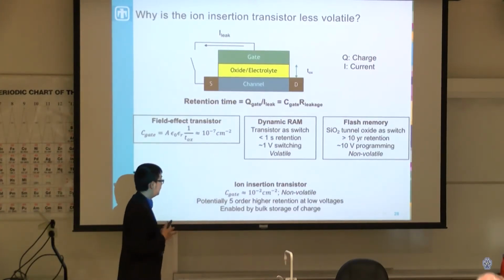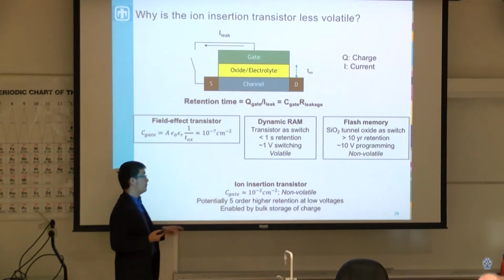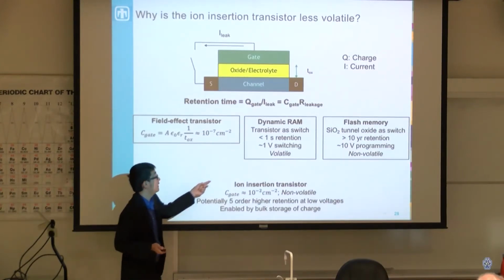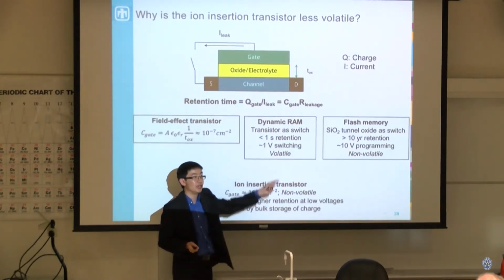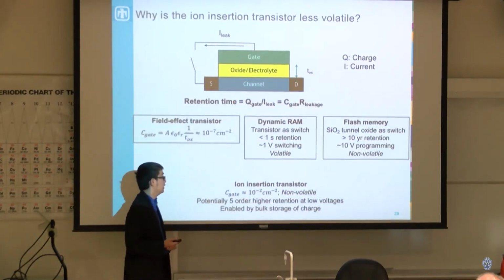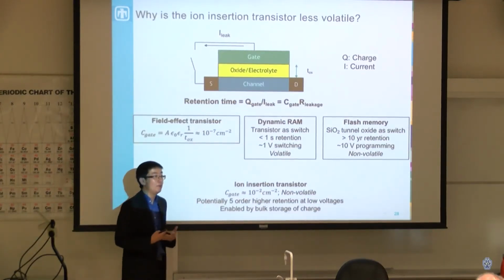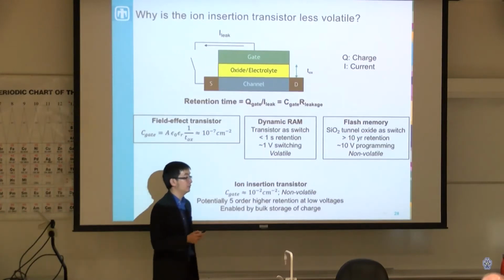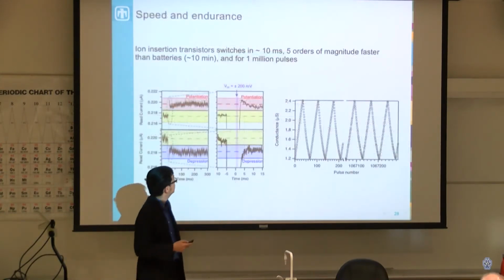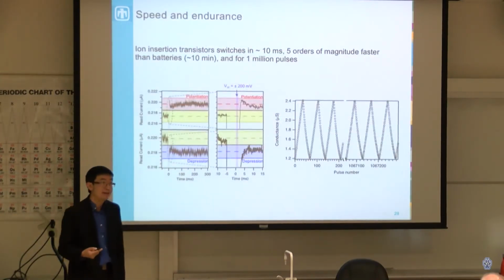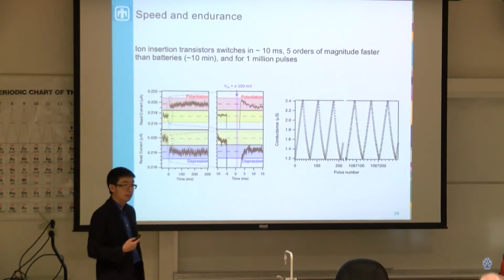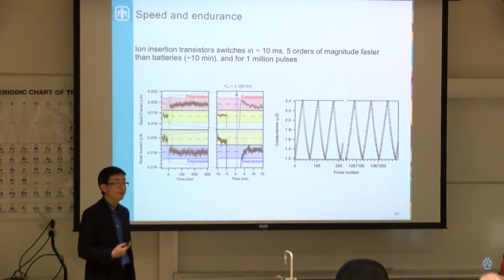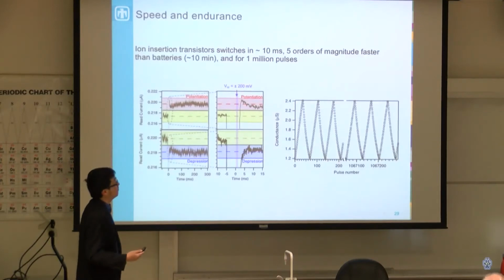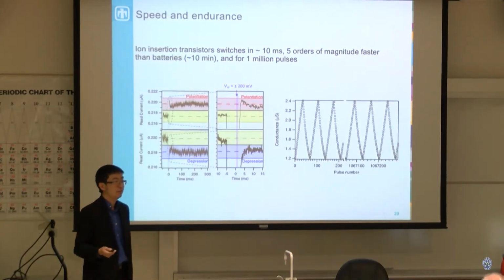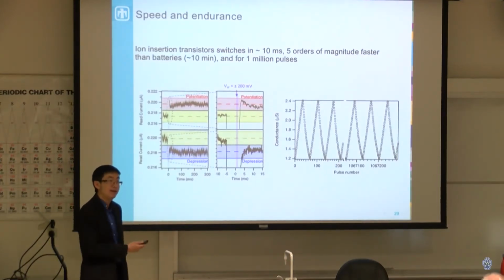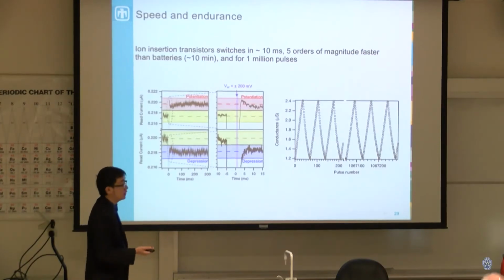So what this can potentially let us do is to have 5 orders of magnitude higher retention, but still maintain the very low switching voltage of dynamic random access memory. So it's ultimately enabled by this ion insertion technology. Our speed is not great in these materials. Because we're having to move matter, we're having to move ions through, we're looking at the order of milliseconds rather than nanoseconds in terms of the switching speed.